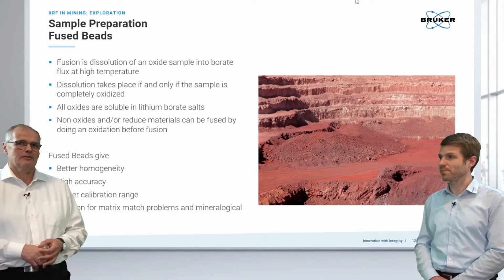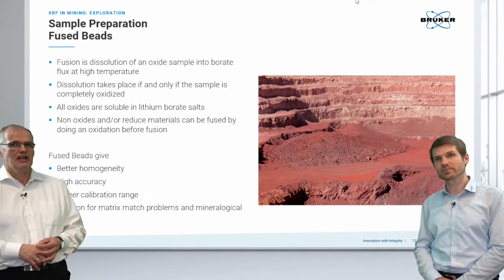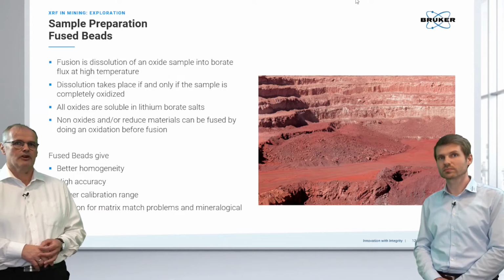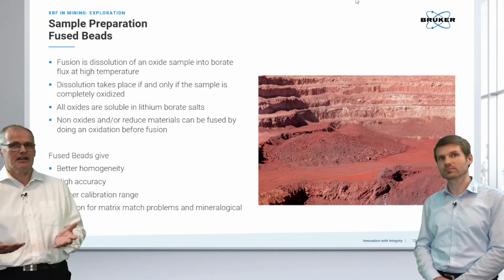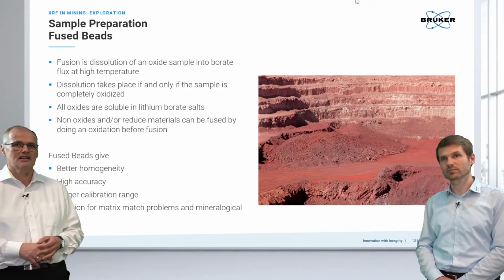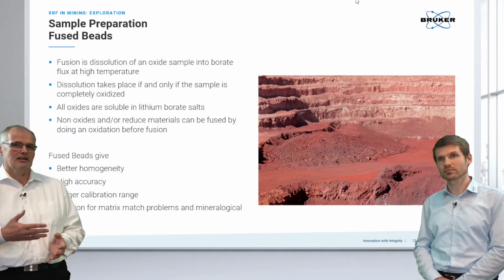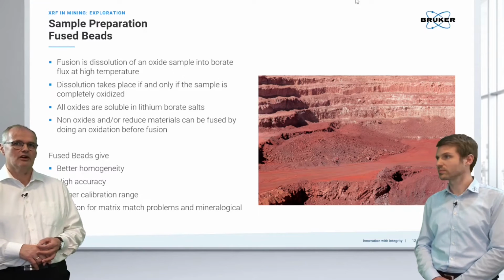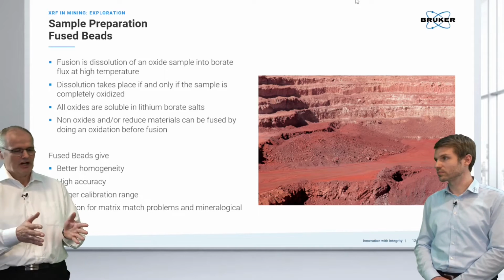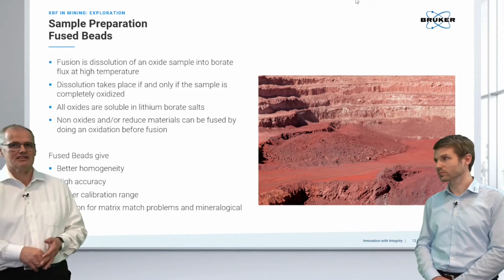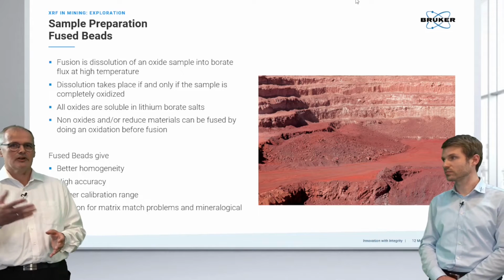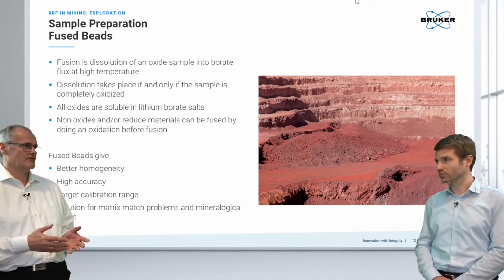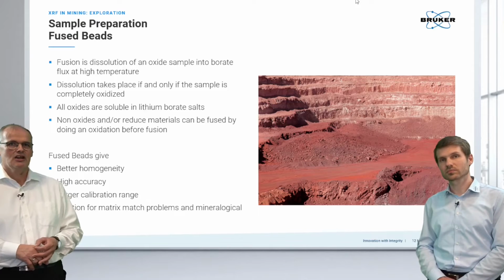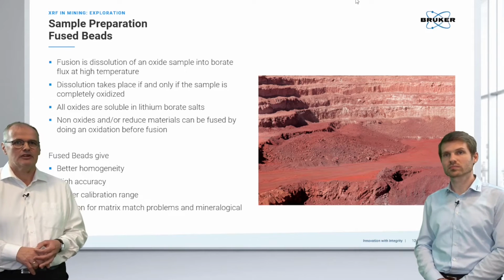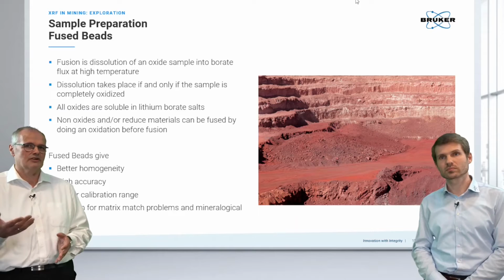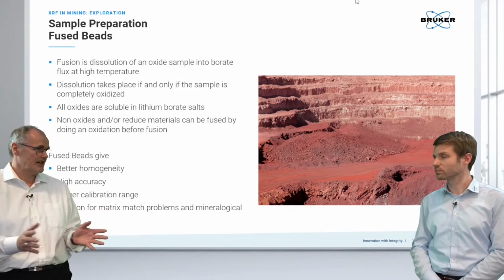So we talked about pressed powder. Nevertheless, fusion is in a lot of applications the preferred method. So what does it mean? We take the sample and we flux it with borate flux at high temperature and put it in a mold and let it cool down. So actually we transform the powder into a glass sample, a homogeneous glass sample. And all different compounds of an element are transferred into stable oxides. And therefore we can transfer almost every mineral into a stable glass sample.